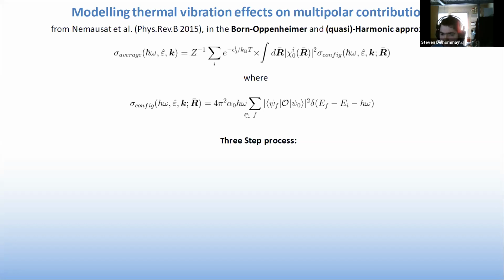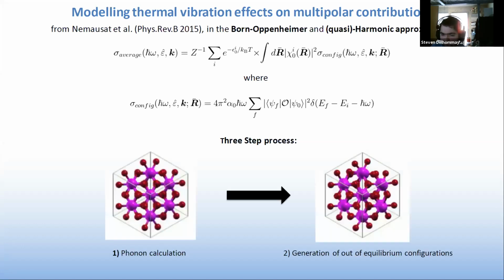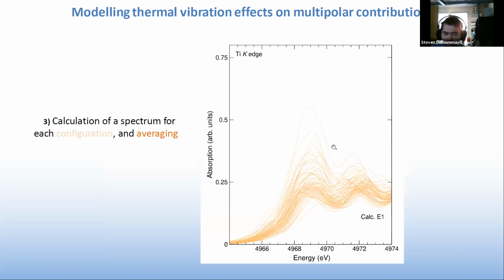More concretely and perhaps more precisely, this is a three-step process. First, we perform a phonon calculation on our equilibrium material so that we can get its vibrational properties. A second step consists in the generation of those so-called out of equilibrium configurations, where we just move each atom from its equilibrium position according both to temperature and the vibrational properties that we calculated beforehand. And the last step is simply, as I told you, to calculate one spectrum for each configuration. So you can see here that each line represents the spectrum calculated for one configuration.